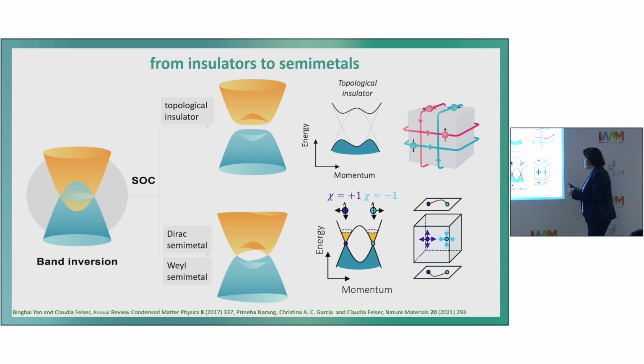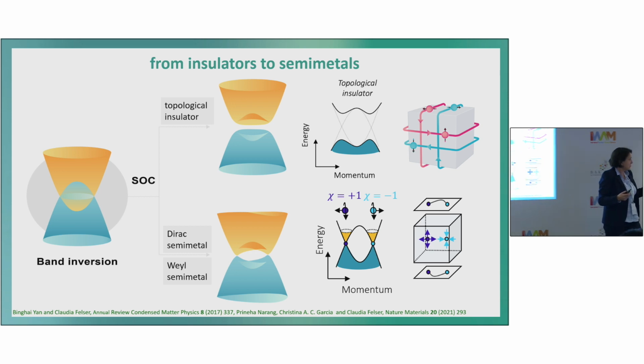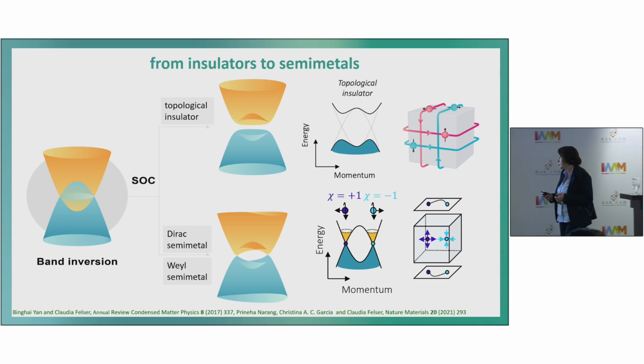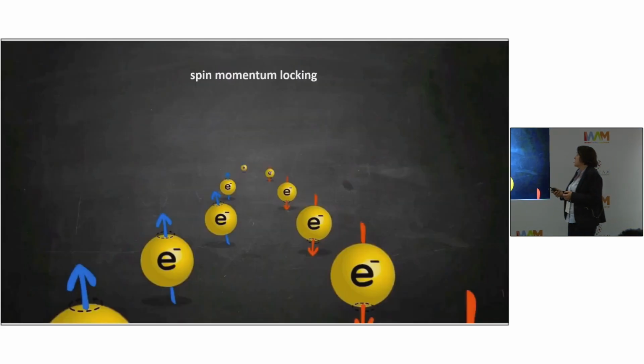So it's very interesting to have these Weyl points far from each other, because then it's not so easy to annihilate them. And this is especially the case, what we will learn today, in chiral crystals, but also in magnetic crystals. It's better than in non-magnetic crystals. So therefore, recently people are working on Weyl semimetals in magnetism and in chirality. So this was what I said: the spin and the momentum are locked.